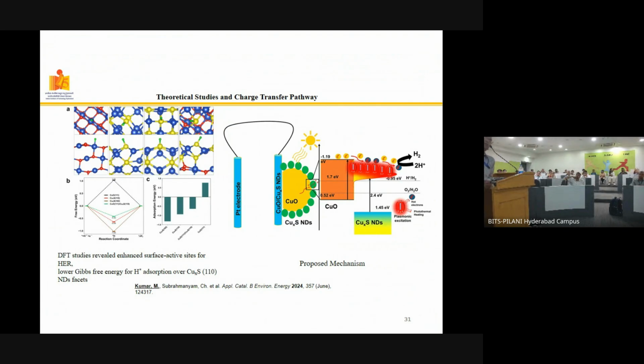With the help of my colleague, we tried to confirm this. The DFT studies revealed that the surface active sites are going to be more and more, especially when you have the sulfide combination, and that's where you are going to favor this. This is also aiding because you are increasing the in situ temperature. Naturally, the energy requirement is going to go down. This is where you have the system.